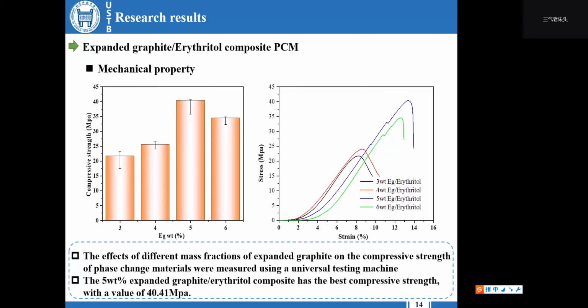Next, the mechanical stress of the composite phase-changing material was measured using a universal testing machine. Among them, it can be seen that 5% expanded graphite erythritol has the highest compressive stress, which is 40.41 MPa, showing excellent mechanical stress.